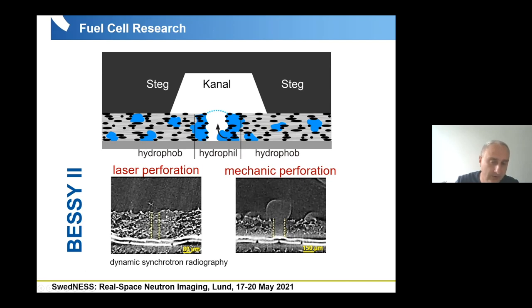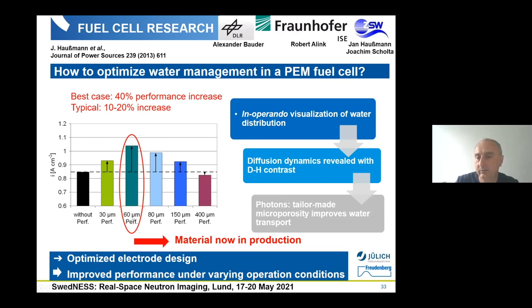where the contrast for water is very weak. But anyway, it was possible to see the distribution of the water for two types of production of these holes, laser perforation and mechanical perforation. And you can see definitely that in the case of laser perforation, the water is here around the channel. And here you can see very well with the mechanical perforation that, even if we have some droplet, the water is clearly staying in the channel. And this helped to increase the performance of the fuel cells by around 40%. So finally, the main result, the very important result here, was provided by the neutron tomography.